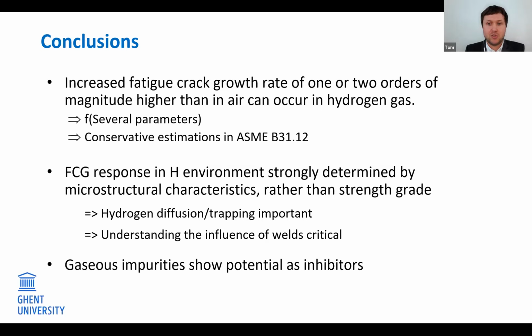The potential presence of weld flaws and also the presence of stress contributions is very important here. And as a final note, the addition of certain gas impurities like oxygen or carbon monoxide to the hydrogen gas shows a lot of potential in inhibiting the hydrogen-assisted degradation of pipeline steels and welds. But again, more research is needed in that field.